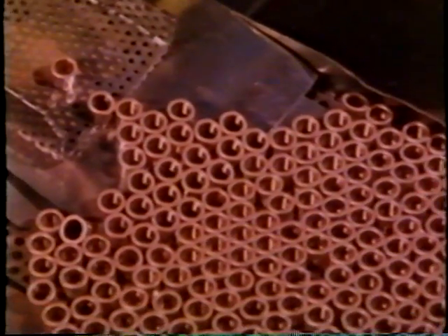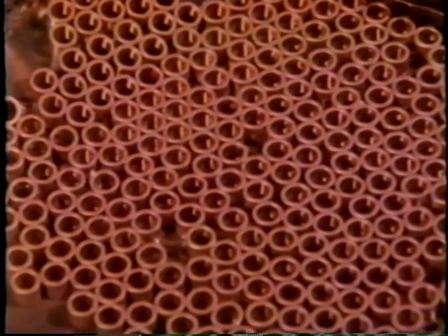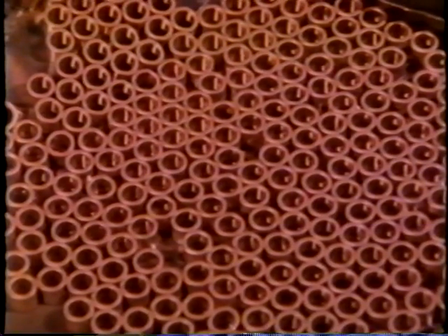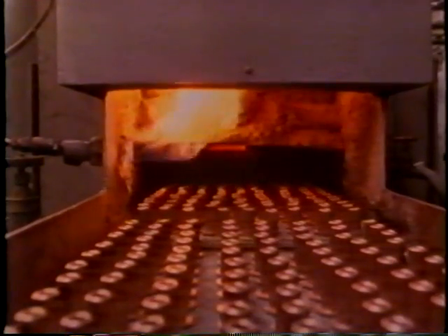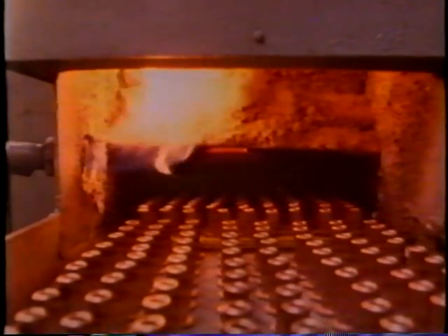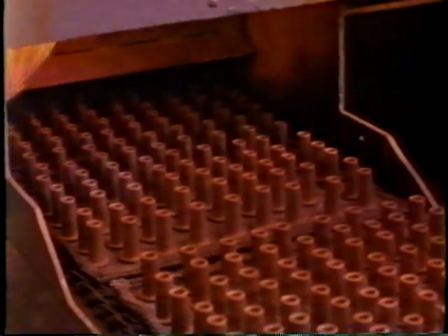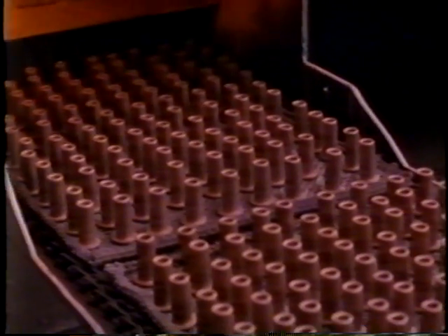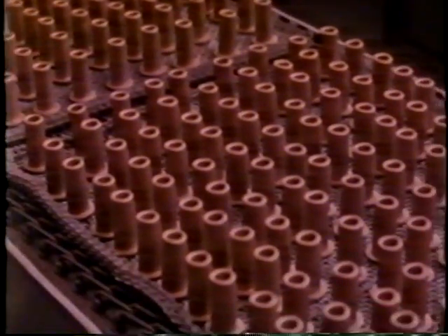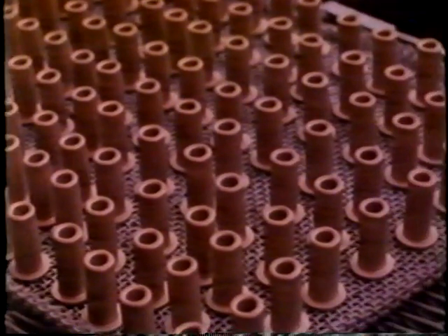At this stage, the porous compacts are quite fragile, and they have to be sintered to alloy the copper and tin. This welds the particles together, forming a porous bronze structure of the required shape. The transformation takes place in an atmosphere containing hydrogen at 800 degrees centigrade. That's well below the melting point of bronze. The result is a tough, porous structure able to withstand relatively high loads.